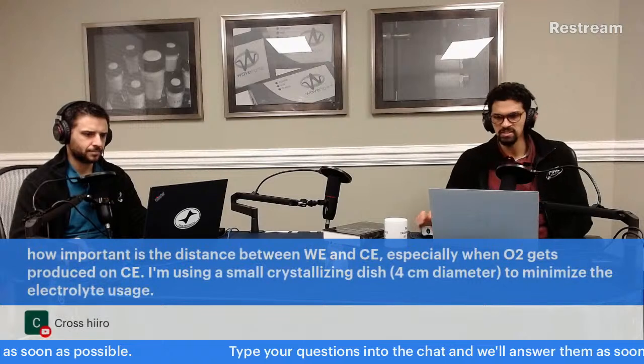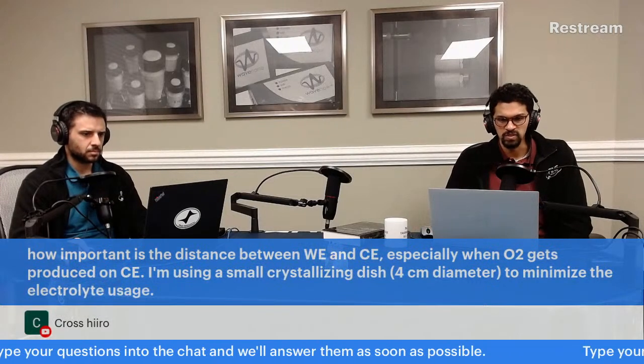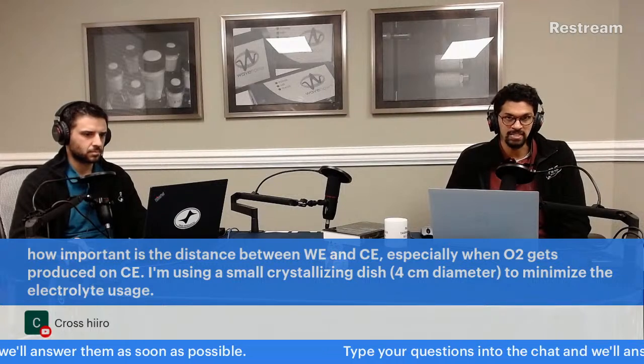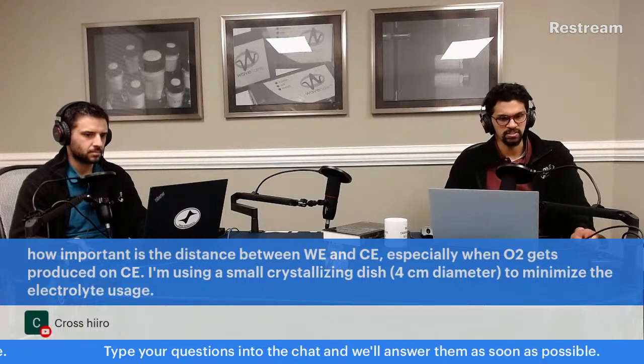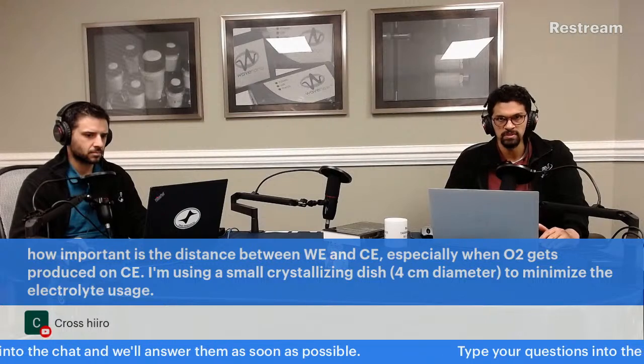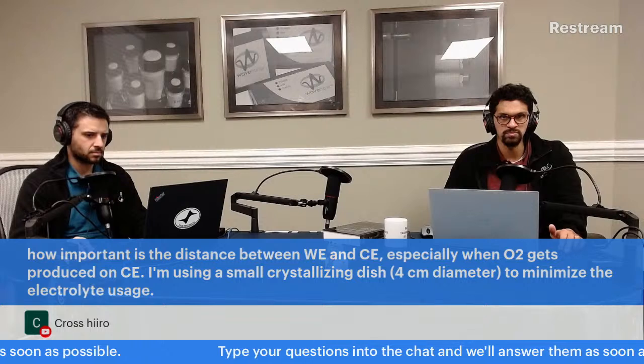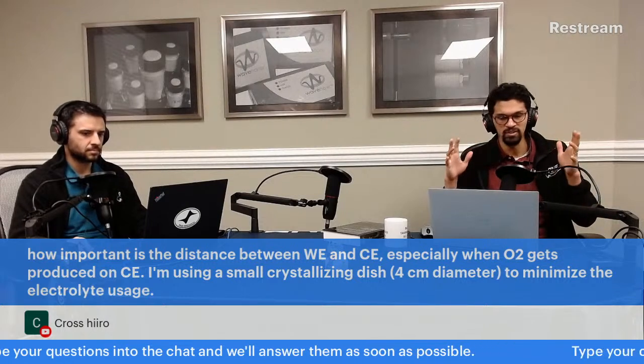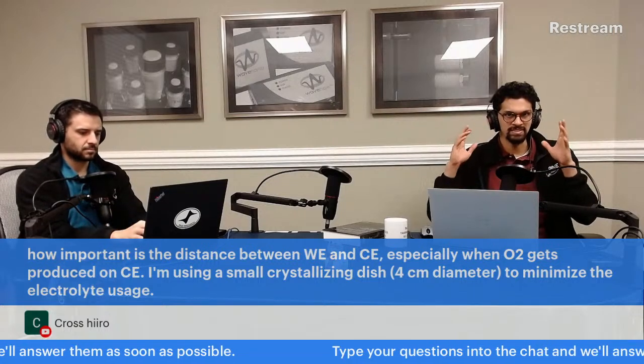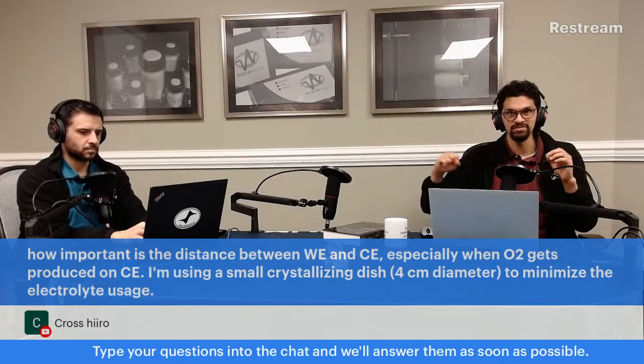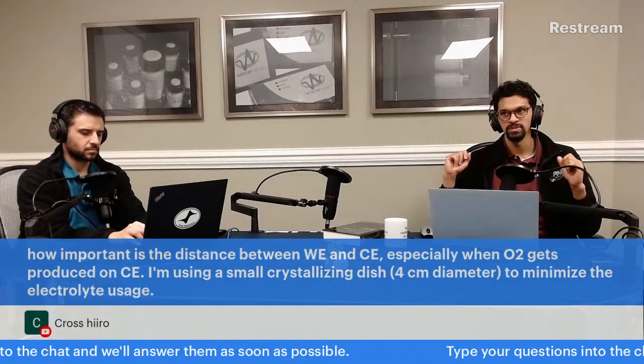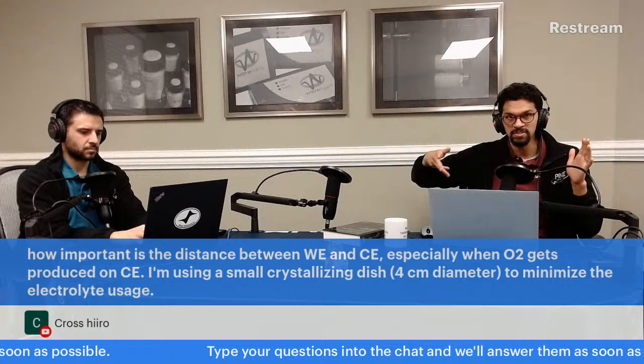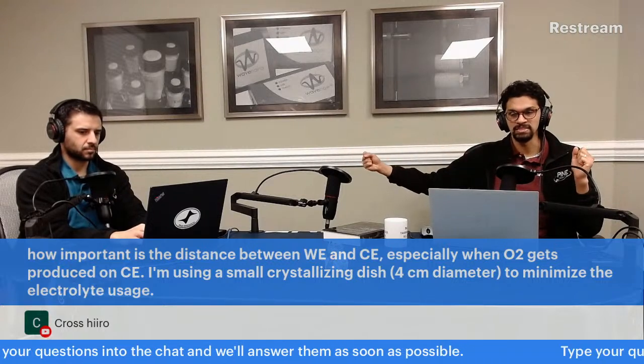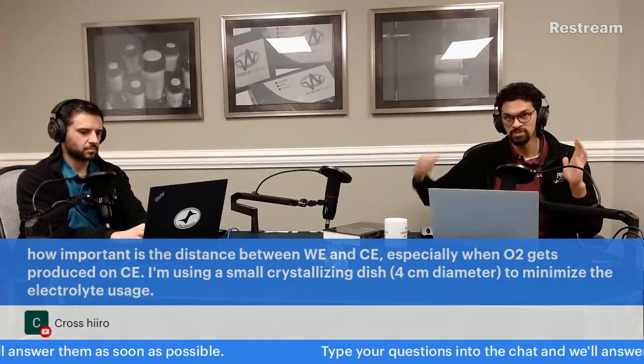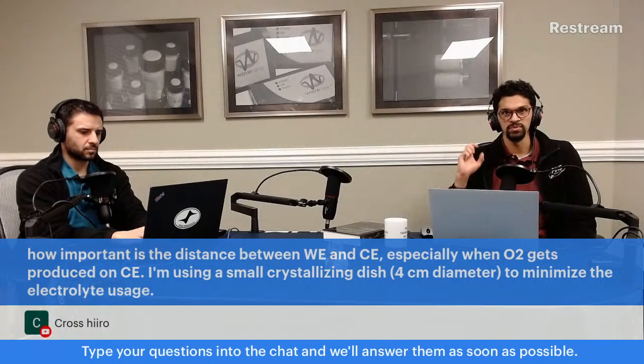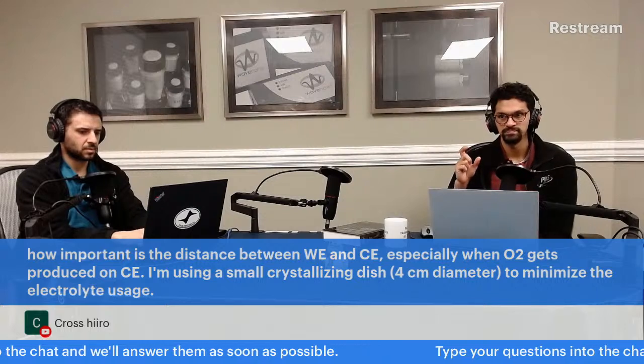So generally speaking, for the distance between the working and counter, you can keep those fairly far. The important thing to keep in mind is that if there's a lot of resistance between your working and your counter electrode, you will run into what's called a compliance voltage issue, which means that you may want +1 volt between your working and your reference electrode. Well, that is established by the counter electrode driving voltage and current through your electrochemical cell. So if there's a lot of resistive elements between the counter electrode and your working electrode, there's a chance it might not be able to reach that voltage that you've set it to. So that's really to say that the resistance is important.